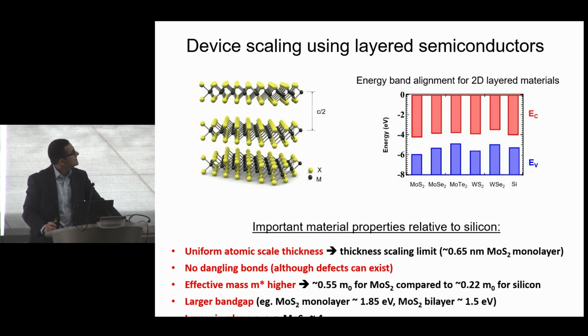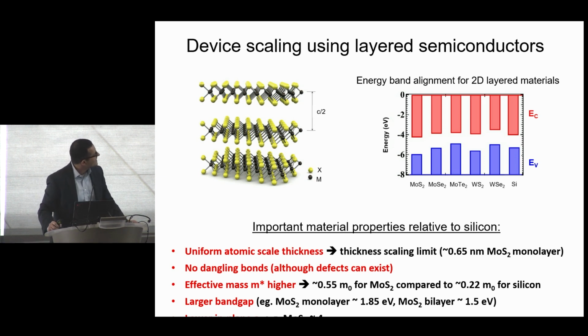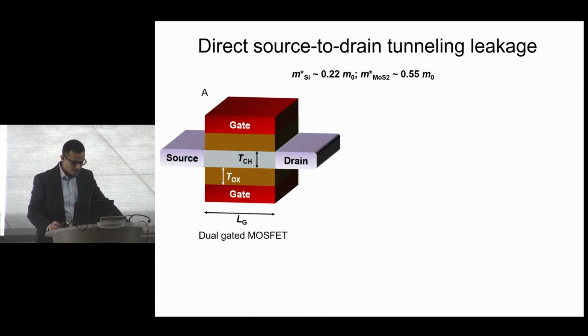Now, if you compare moly sulfide specifically against silicon, you can beat the thickness scaling limits. These are materials that have no dangling bonds. Of course, defects exist. And you can make materials that are a monolayer with atomic scale uniformity. Effective mass for MoS2 is significantly higher compared to silicon. The band gap is significantly higher. The band gap of 1.85 eV is vastly underestimated. There is a large exciton binding energy. The actual band gap, the transport band gap, is over 2 electron volts. And of course, a significantly lower in-plane dielectric constant.